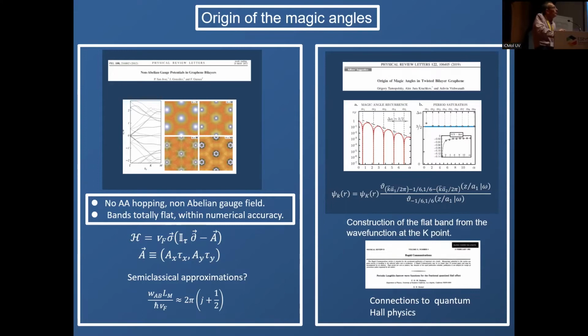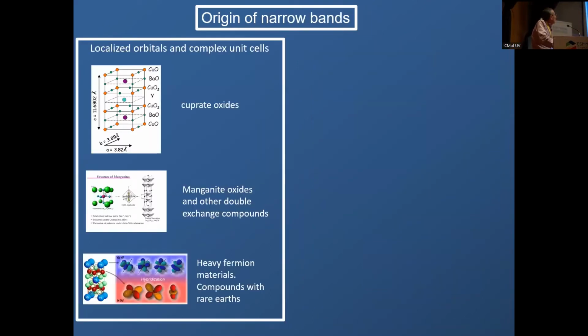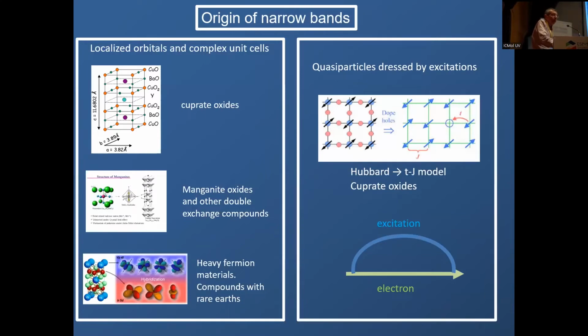So graphene seems to be a material very far from a simple metal in a magnetic field, especially because the bands are derived from highly localized p orbitals, p-z orbitals on the carbon atoms. But nevertheless, the flat bands which come out of these calculations for twisted bilayer graphene, they do resemble somehow the Landau levels you have in a regular metallic two-dimensional system in a magnetic field.